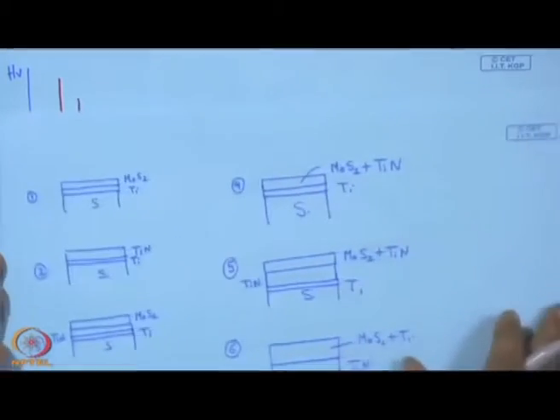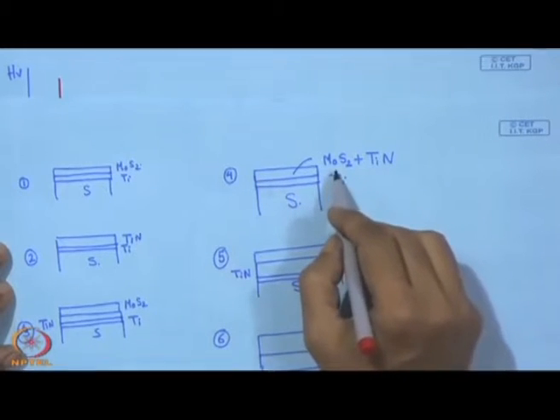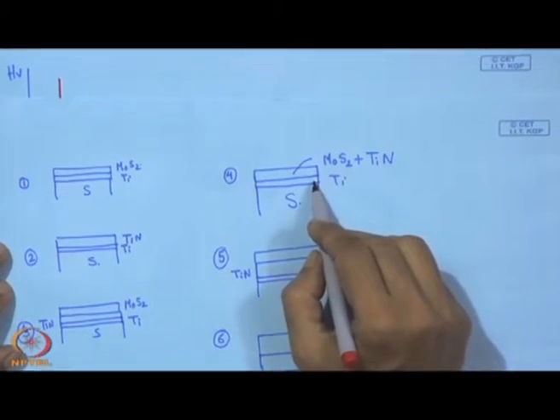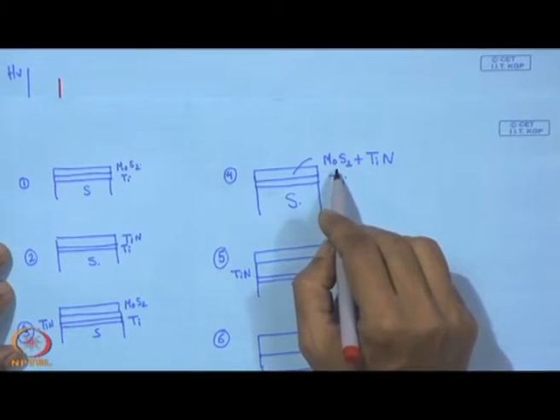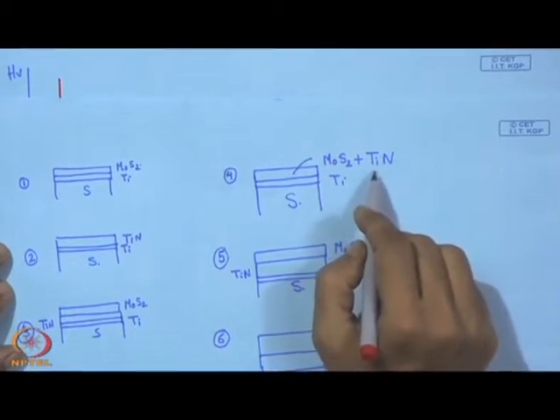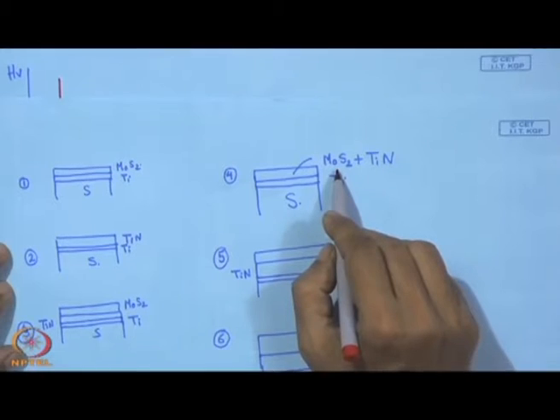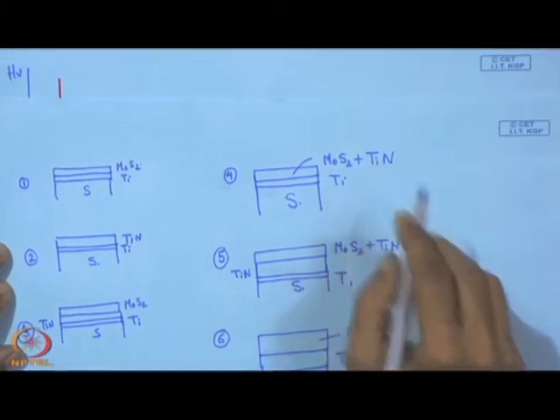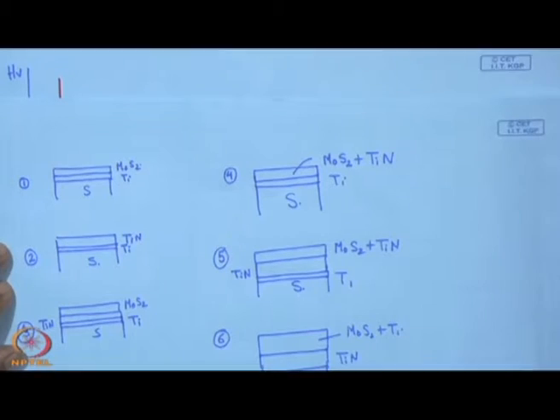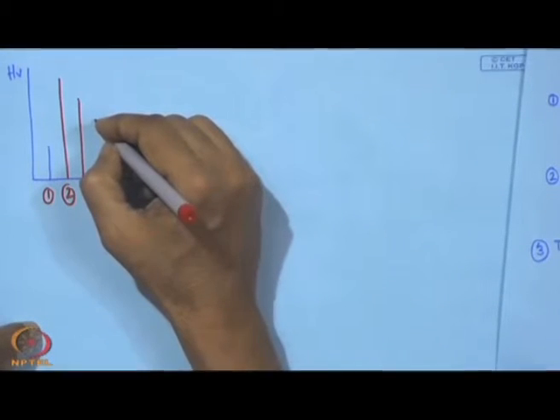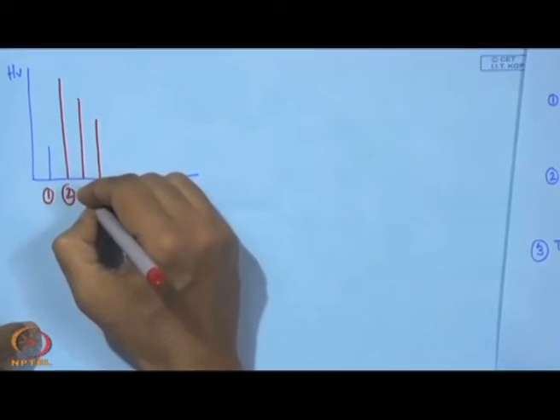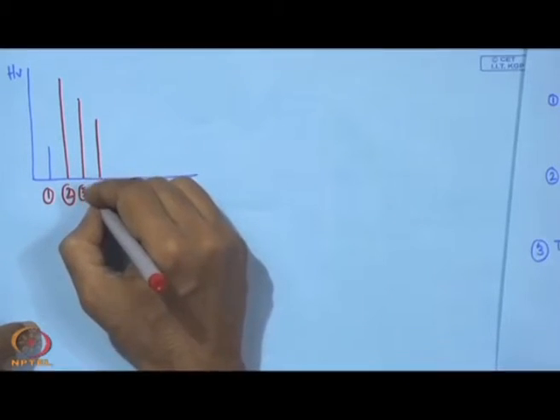In number 4 what we can see here is that it is a composite coating, but with no support layer of TiN. So, it will give a bulk value which will be more than MoS2, but it will be less than that of TiN. So, naturally when we see this value of TiN, then definitely this will be less than that one. So, we have something somewhere here, and this is going to be 3 and that is going to be 4,